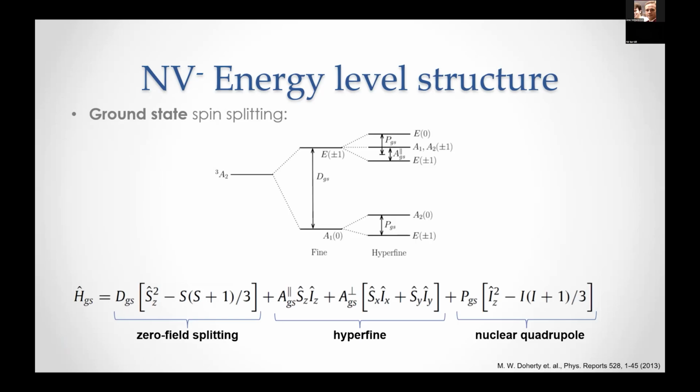That hyperfine coupling then splits the states within the plus minus 1 manifold. The nitrogen is mostly nitrogen 14, an isotope with a nuclear spin of 1. So it has 3 sublevels, which you can see the splitting of here. Sometimes you can find N15 isotopes with a spin half, and there you'll see a double splitting and not a triple splitting here.